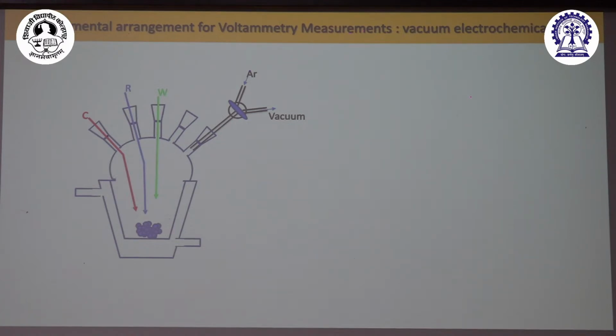And we heated this by passing hot water, so that my cell temperature becomes 80 or 90. And now I apply vacuum. So what will happen now? In situ, I am drying my supporting electrolyte, because the temperature is 80-90 and I am applying vacuum. Once I have dried my supporting electrolyte in the cell, I injected the solvent and the quantum dots. And again I applied vacuum and argon, vacuum and argon 3-4 times, so that my atmosphere becomes moisture free. And then we did the experiments.